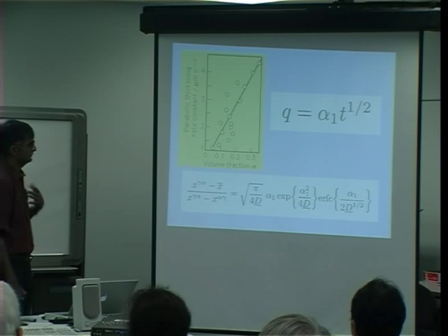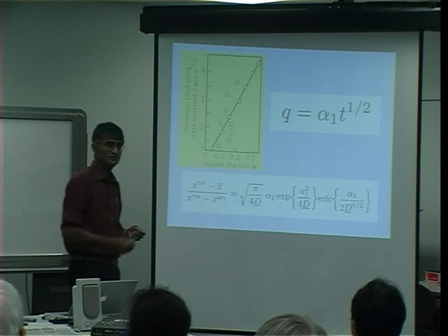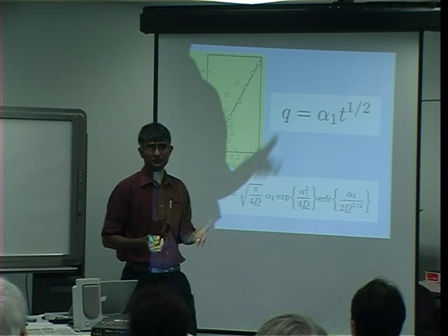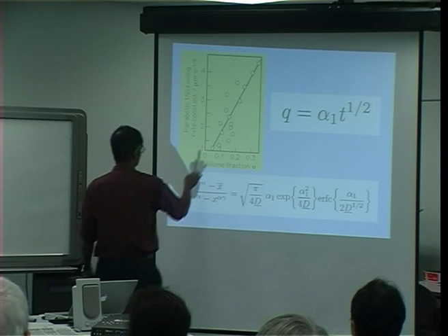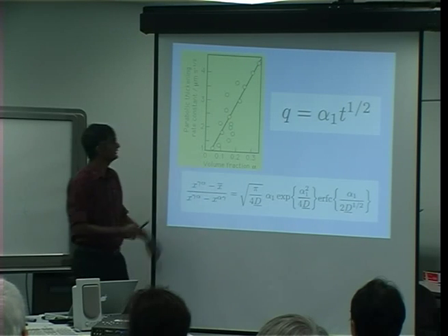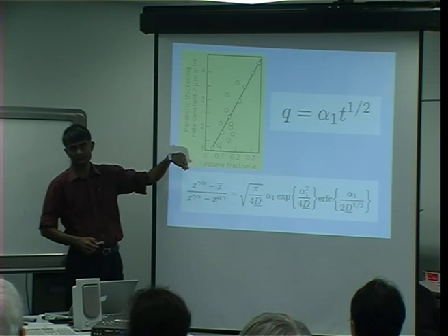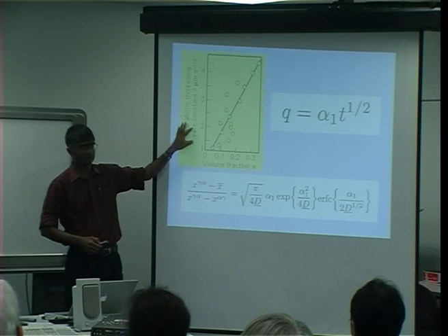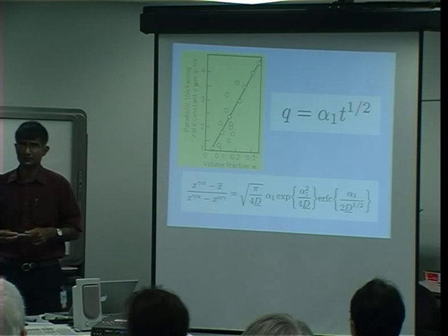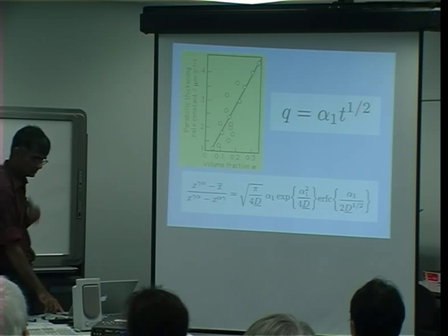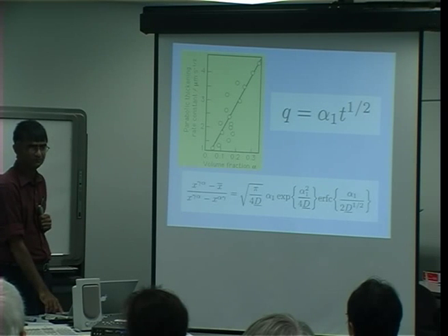So supposing that our assumption that nucleation can be ignored is correct, then we ought to have a correlation between the volume fraction of ferrite and the parabolic rate constant. Each point here represents a different welding alloy, and you can see there is a good correlation between the parabolic thickening rate constant and volume fraction, justifying that let's forget about nucleation theory and just treat this as a growth problem.